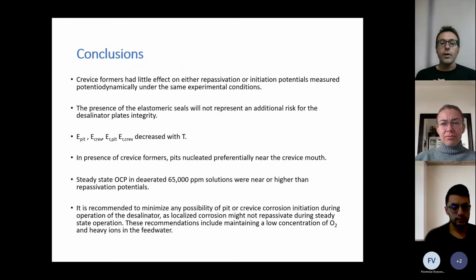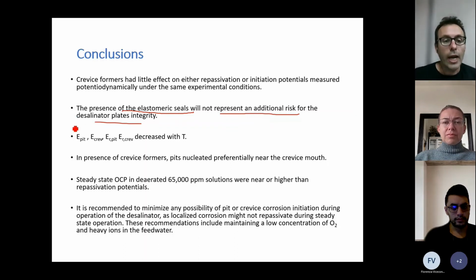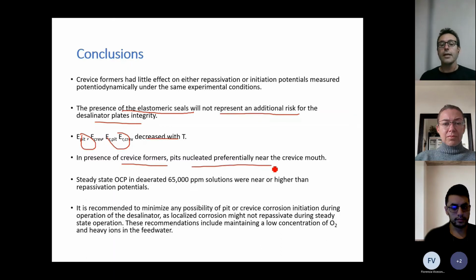So the conclusions of this study were, first, the crevice formers had little effect on either repassivation or initiation potentials measured potentiodynamically under the same experimental conditions. So in practical terms, this means that the elastomeric seals will not represent an additional risk for the desalinator plant's integrity. Localized corrosion initiation and repassivation potentials decrease with temperature as expected. So when you are up in temperature, localized corrosion is easier to initiate and more difficult to repassivate. And when we have crevice formers, the pits preferentially nucleated near the crevice mouth.